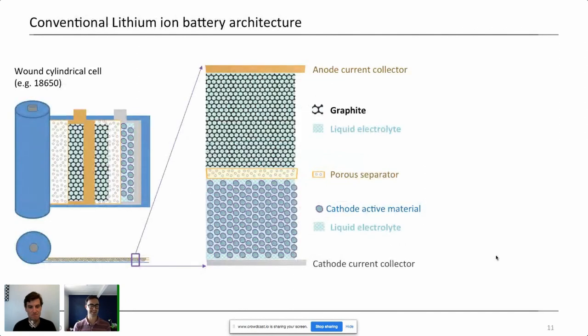So now we're gonna dissect a battery so you get a little bit of a better idea of what's inside this cylinder. So this is what's inside a lithium ion battery. It's not at all what's inside an alkaline, like an A or AA or AAA battery, but inside a lithium ion battery, you'll see some version of this. This example shows a wound cylindrical cell like what's inside Teslas today. Most other automakers have a different form factor, but once you unroll what's inside, you'll see the same thing, which is essentially five sheets, two of those that contain active materials and three of them are inactive but structural.